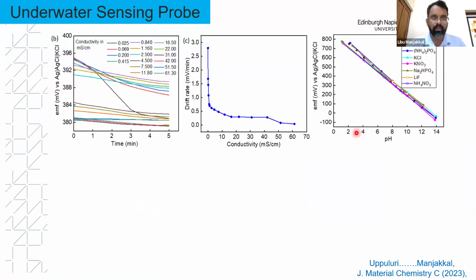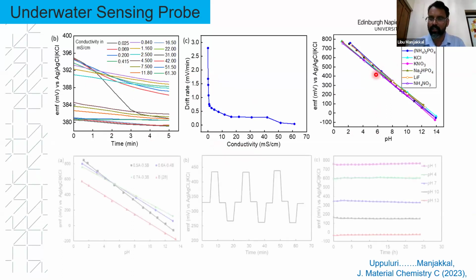And then we monitored with that underwater sensing probe. For example, in a river, the salt level and the water conductivity level may vary. So we monitored the sensor at different conductivity levels of the water, and we also kept the sensor at different conductivities to see the drift variation, how much the drift is, and the selectivity issue of the water when sensing in different fields.